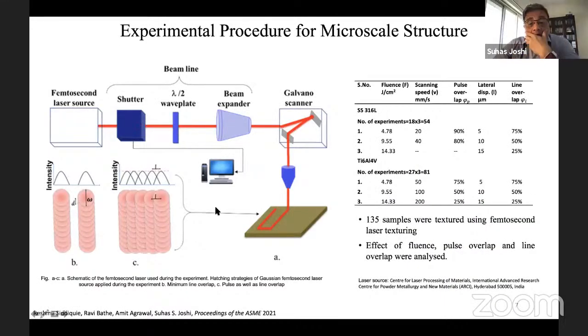In the second case, we have used femtosecond lasers to scan the surfaces in two or three different fashions, in a way that there is a pulse overlap, where the laser pulses are overlapped one on each other, and the overlap could be 25% to as high as 90%. And then besides the pulse overlap, we have line overlap also. So the first line is overlapped by the second line, again up to the extent of 25 to 75%. And then this can give rise to a variety of micro scale structures.